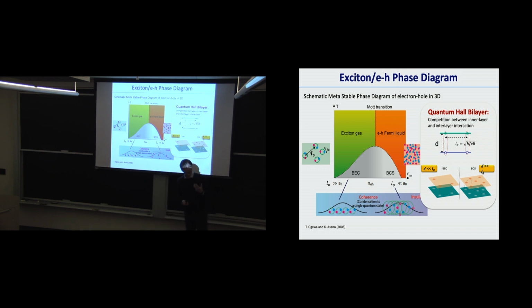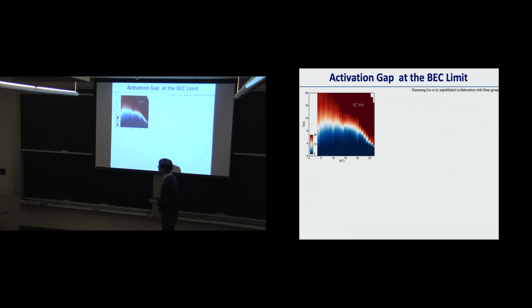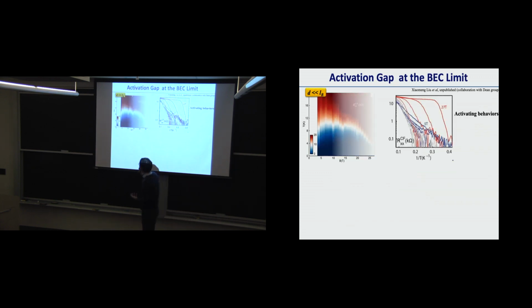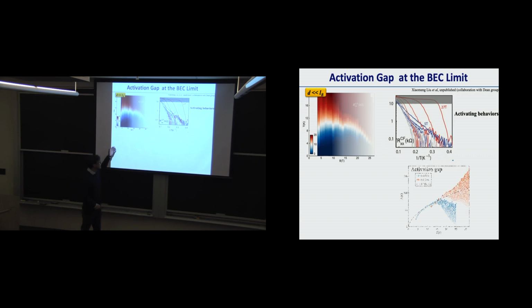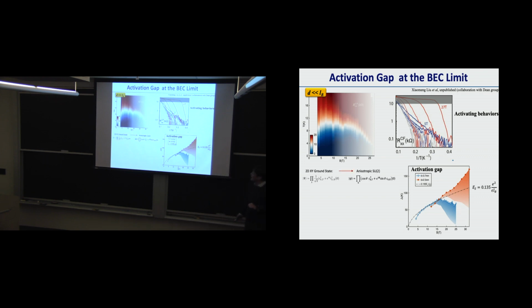You can actually analyze this a little bit more in detail. For example, if it's in the low magnetic field region, the so-called BEC limit, you can see why we actually have this type of activating behavior. In fact, in this BEC limit, once you extract the activation gap, it's actually nicely scaled with the Coulomb energy that governs this regime, which is more or less expected when you write down the magnetic exciton.